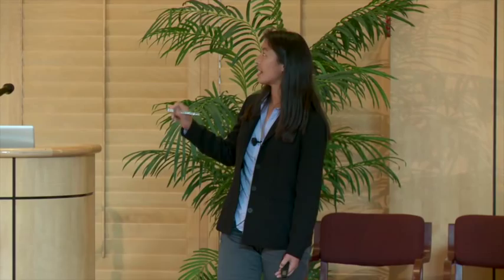And I just want to highlight here some of the reasons that we're working on copper is to try to improve these deficiencies. So the first is, on this plot, we have the potential versus a scale that we call RHE. Zero is where the thermodynamic minimum is at. And then we have efficiency for a variety of different products. So at low potential, you can see that all we're making is hydrogen. That's the product we don't want. However, as you ramp up the potential, the hydrogen starts to go down. And we start to see some of these other products, including CO and formate. And then you ramp up the potential a little bit more, and you see ethylene and methane, which are our target products.